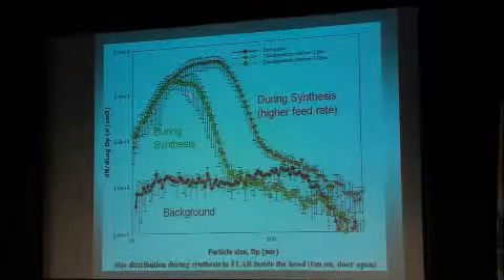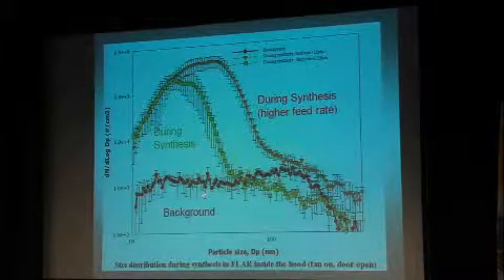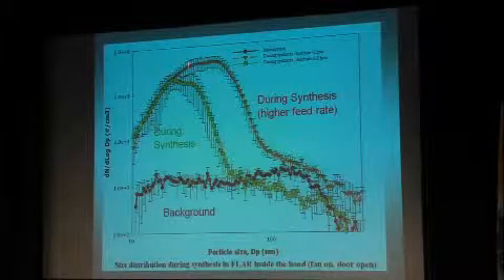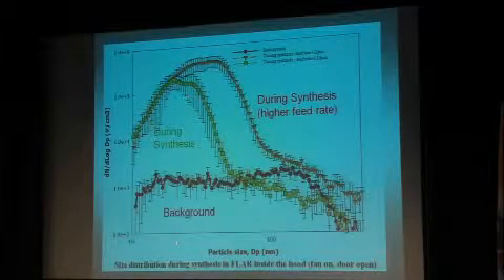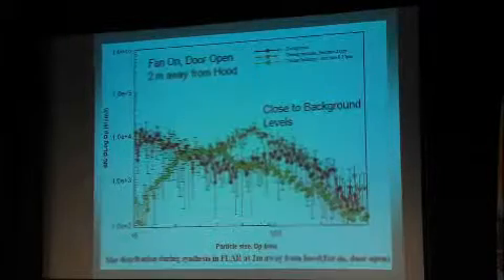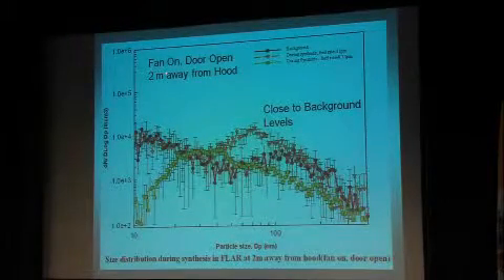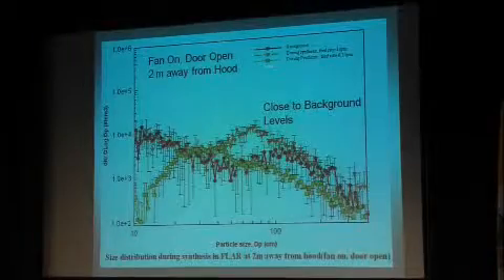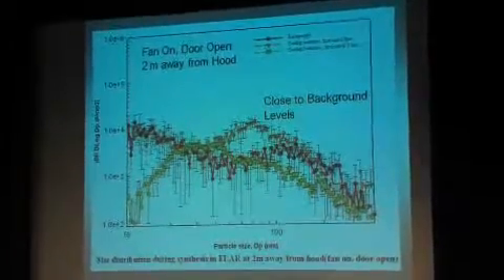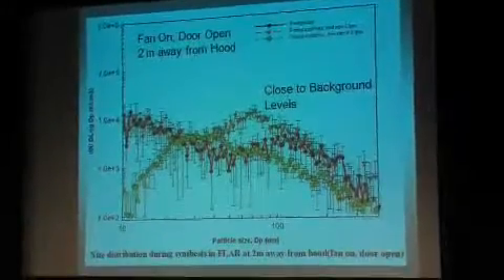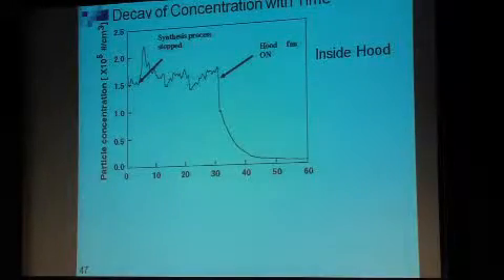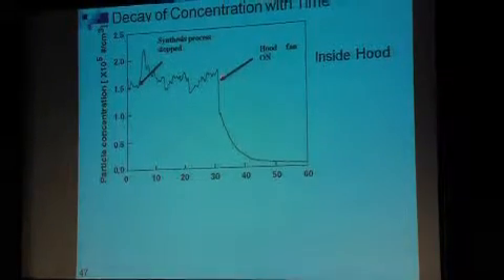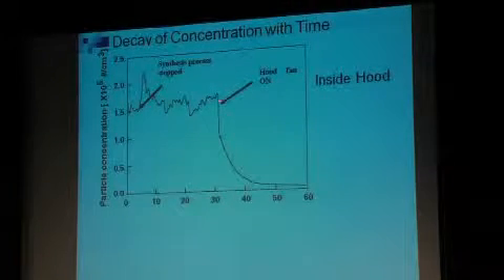These are different setups. I can go off design conditions. I can say that my hood is not functional, and you can see inside the hood during synthesis, this is the background concentration. The concentrations shoot up. I'm, of course, making nanoparticles in a flame environment, and you can see that outside the hood, even if the door is left open, because the hood is functioning well, the concentrations are very close to the background level. This is good, but good to know. But then you see that when you stop synthesis, firstly inside the hood, high concentrations.